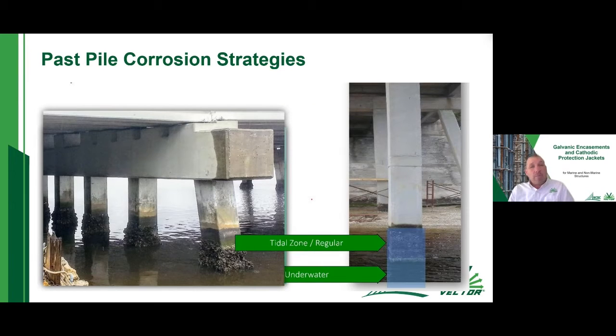And so with that, a cathodic protection jacket system was developed for the underwater portion, or the tidal zone portion, that I had just talked about on the previous slides. We have a lot of salt water, so we have a lot of low resistivity in here. So it's very easy for corrosion to occur, and when it happens, it just continues at a high rate in here as well.